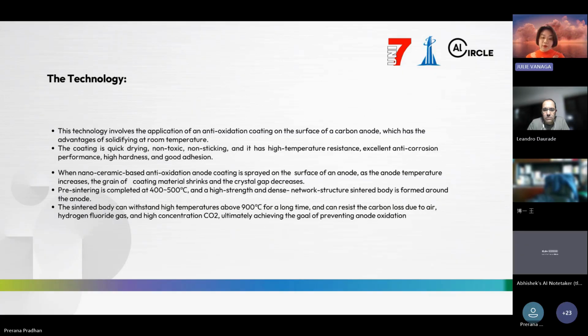And then we're going to talk about the reaction process of the spraying. When our nano-ceramic-based coating is sprayed on the anode surface, a fascinating physical and chemical change happens as the anode temperature rises. The grains of the coating material shrink gradually, and the crystal grains become smaller and smaller. When the temperature reaches around 400 to 500 degrees, it will sinter. When the temperature reaches 400 degrees, the coating completes pre-sintering and a high-strength, dense network-structured sintered body forms